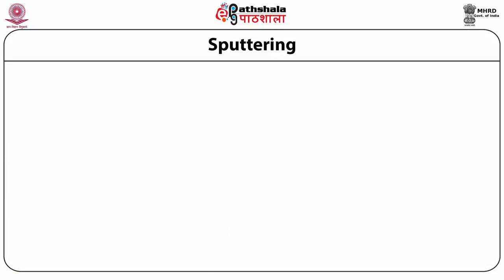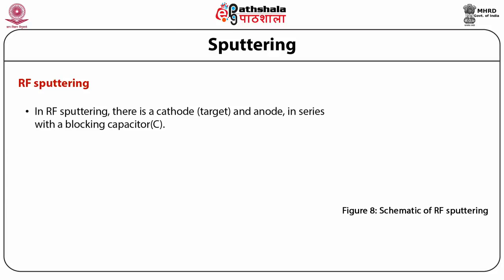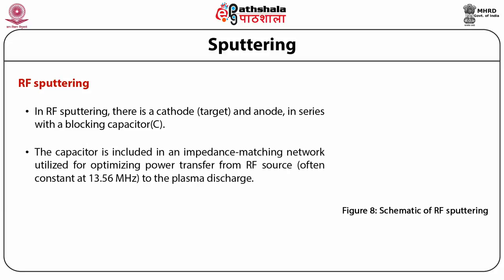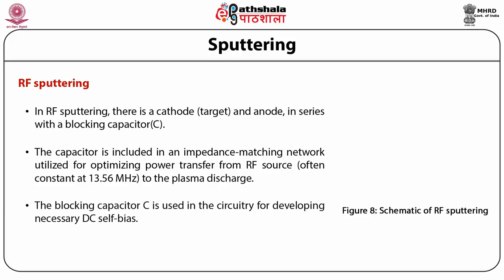Next type of sputtering is RF sputtering. So this figure shows a schematic of RF sputtering. In RF sputtering, there is a cathode, that is a target, and an anode in series with a blocking capacitor C. The capacitor is included in an impedance matching network utilized for optimizing the power transfer from the RF source, often constant at 13.56 megahertz, to the plasma discharge. The blocking capacitor C is used in the circuitry for developing the necessary DC self bias.